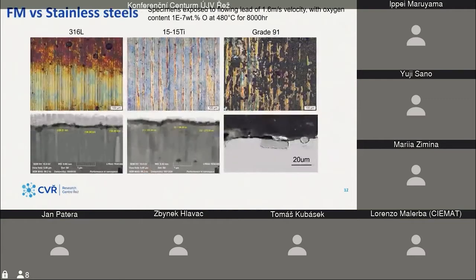So some results. These specimens were exposed for 8,000 hours in controlled lead with oxygen level 1e-7 weight%. It's something like 400 micrograms in the loop. The difference between austenitic and ferritic steel is that austenitic steels cover themselves with an extremely thin layer that is barely visible. On the other hand, the grade 91 steel grows a very thick magnetite layer that somehow protects it. This is the key difference.